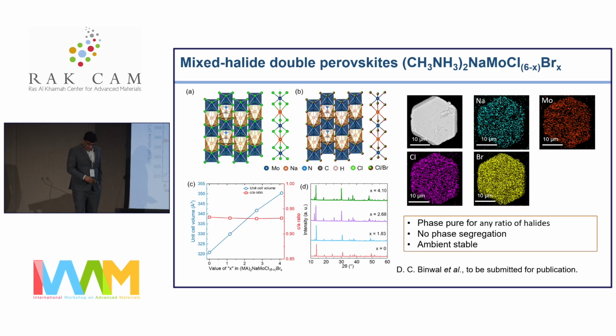And then very recently, as Professor D.D. Sharma mentioned, the properties, particularly the optoelectronic properties of halide perovskite, can be tuned by mixing halides. So here we have a series of examples where the optoelectronic properties can be tuned by mixing 2 halides. Here it is the sodium-based compound, sodium molybdenum chloride, the parent compound. In that, we can keep increasing the bromide content and get a mixed halide situation, where the chloride and bromide are basically occupying the same crystallographic site.